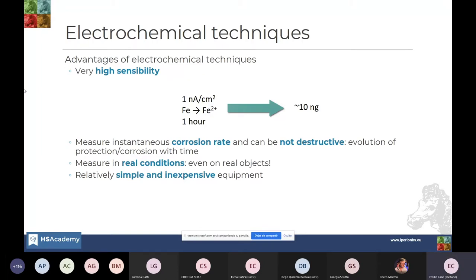And in some cases, we will talk about this a bit later, it can be non-destructive. So we can measure the evolution of the protection system or the corrosion over time. We can also measure in real conditions. We do not need to take the sample to a microscope or to another analytical technique. And this is very important in our case, in which we need to measure on real objects, on real artifacts that cannot be moved. And finally, it is relatively simple and inexpensive equipment, mainly if we compare with other analytical techniques.